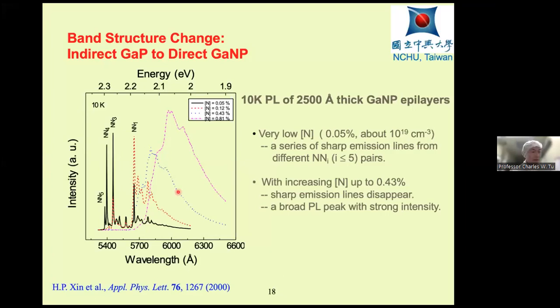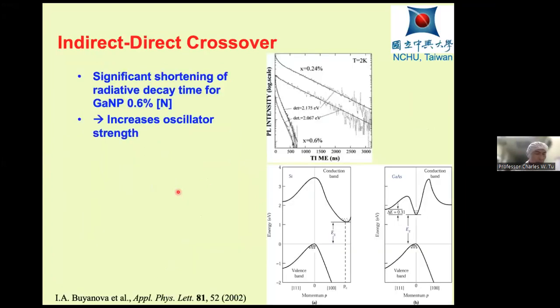And indeed, we collaborated and sent the samples to Professor Buyanova at Linköping University. First, here I show the difference between the direct and indirect band gap. You see here, once again, it's the energy as a function of momentum or wave vector. For an indirect band gap, like silicon, the minimum of the conduction band is some momentum away from the maximum of the valence band. And gallium arsenide is a direct band gap. So direct band gap materials emit light.